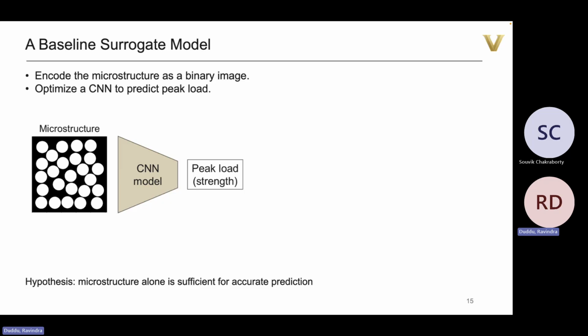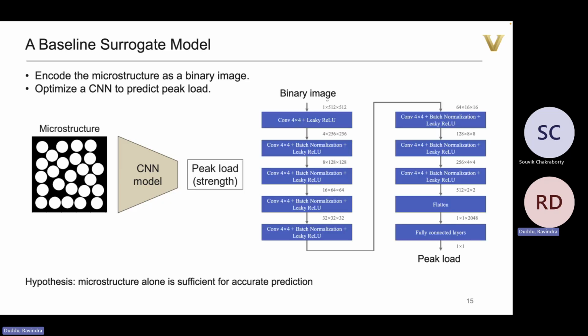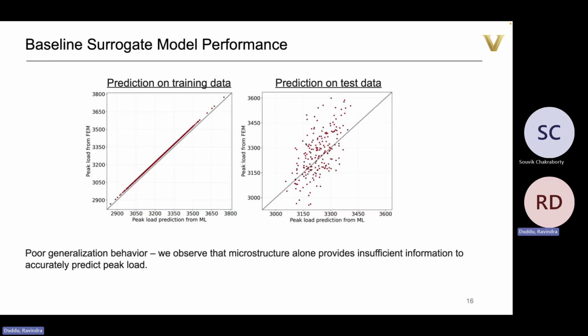So this type of model is called a VGG16 type model. You probably know the sort of architecture. Some of you. You take an image, you have some resolution, you go from a high resolution to a low resolution, but more channels and so forth. And then eventually you do some flattening, batch normalization, and you get one scalar peak load, right? So this is the baseline model, the simplest one, and it has been applied in some publications. There's one publication in the Computational Materials Science journal that we looked at.